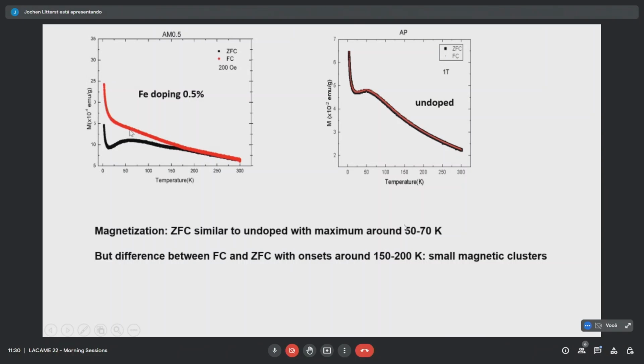It's easily explained. If you dope in iron, you may have in part small correlated clusters. It may be small iron clusters that are somehow formed. Which kinds they are, we do not yet know. But in principle, at least in zero field cooling, it looks very similar to the clean compound.